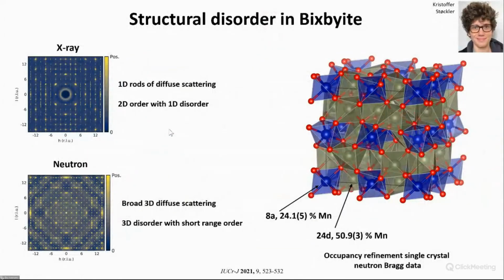But of course, this structure also has structural disorder because you have the iron and manganese sites. And this is very, very hard with X-rays to distinguish between iron and manganese, but with neutrons, you of course have negative and positive scattering lengths. So if you do the single crystal X-rays, you see, I think you can see here, these long rods going down. So we are back in the same situation as copper selenide. There's probably some 2D order with 1D disorder. Whereas in the neutron diffuse scattering, you see this very slowly varying, very broad diffuse scattering. So that's probably some short range order that gives rise to this.